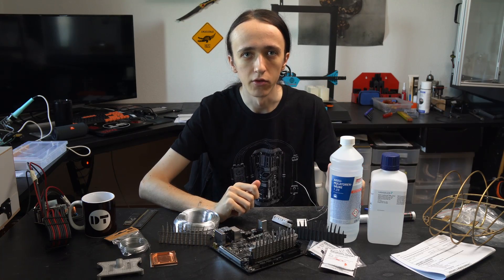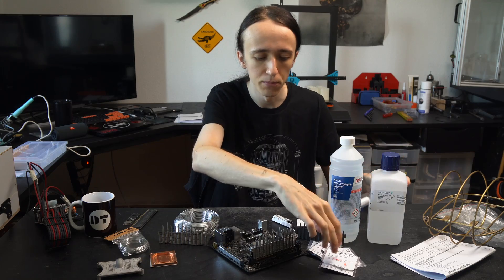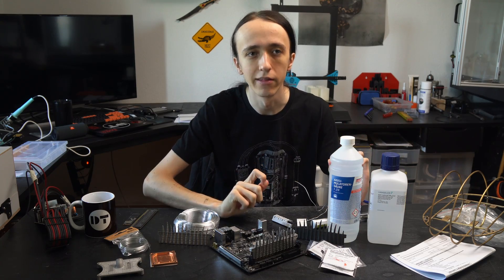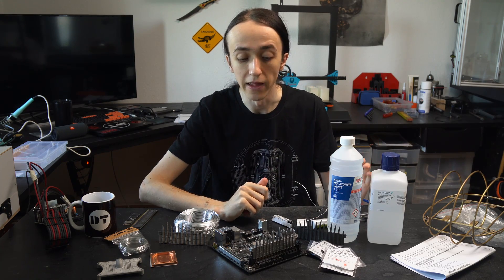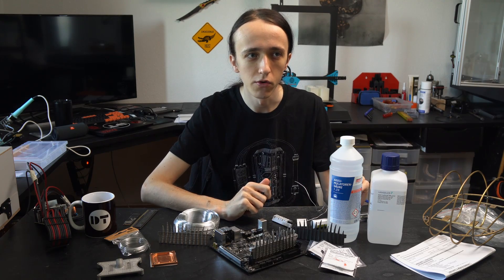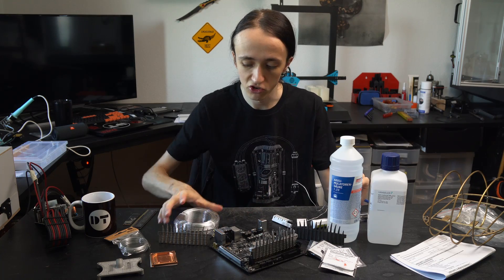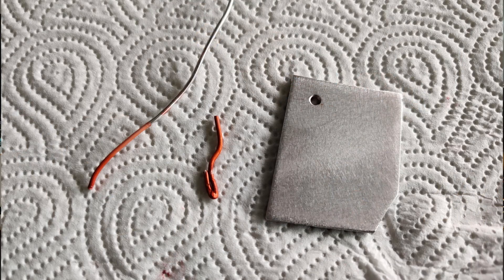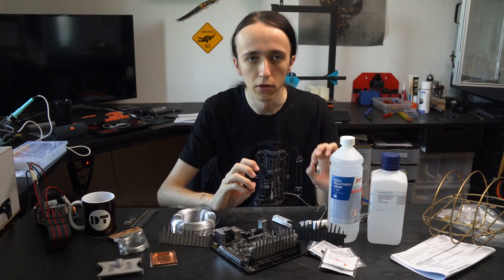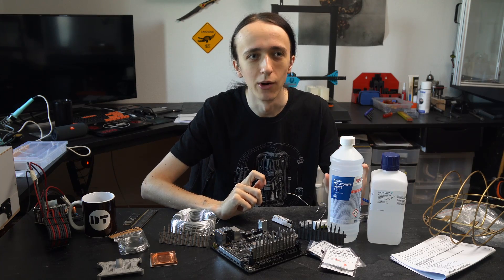The other things you need are a power supply and a temperature sensor of some sort, since you want the dye above 50°C when using it, so you'll also need a hot plate. Before going in with my fancy 3D printed parts, I did a test part. It didn't anodize properly — I'm pretty sure I had bad contact. The aluminum wire, which you'll also need, anodized beautifully though. I was going for a copper color, and the wire came out super beautiful; left in longer it turned more reddish, but as an intermediate step it looked just like copper wire, which is really cool.